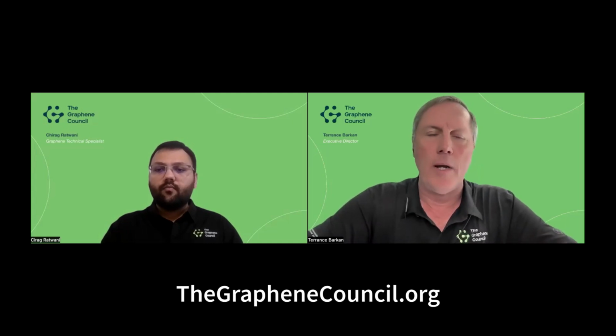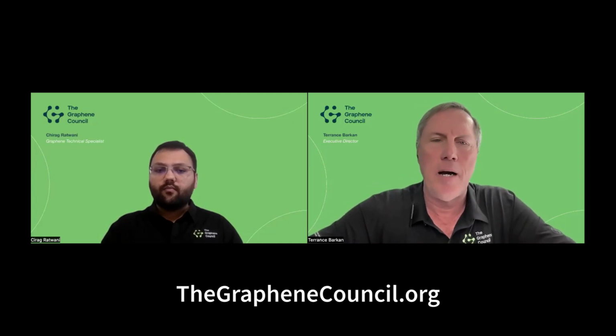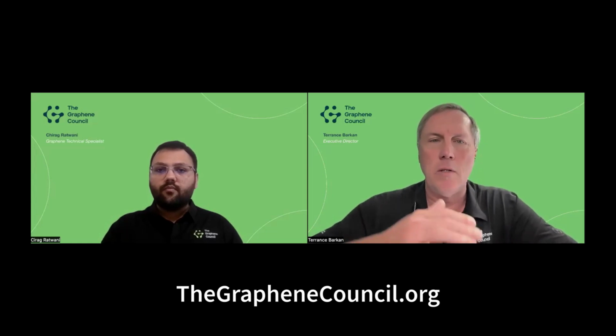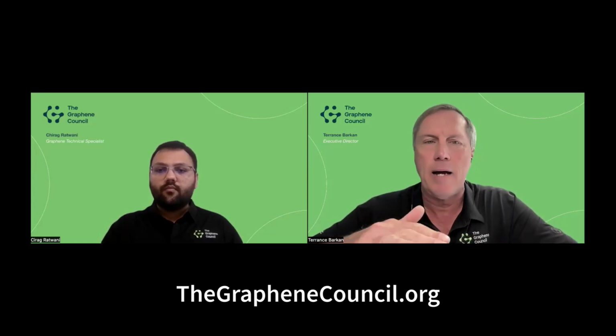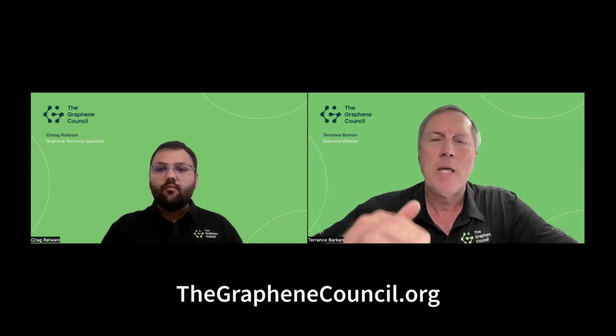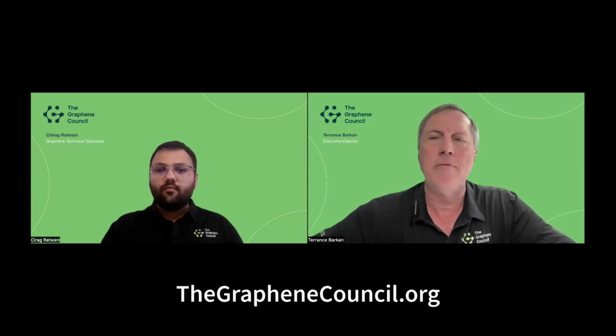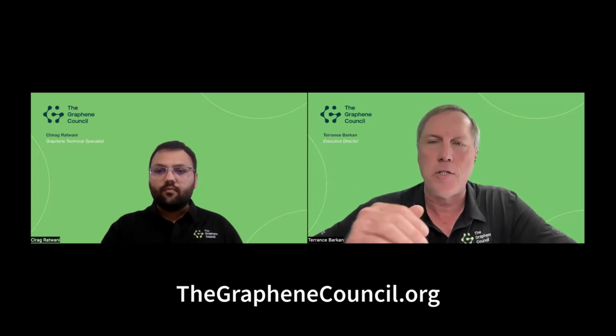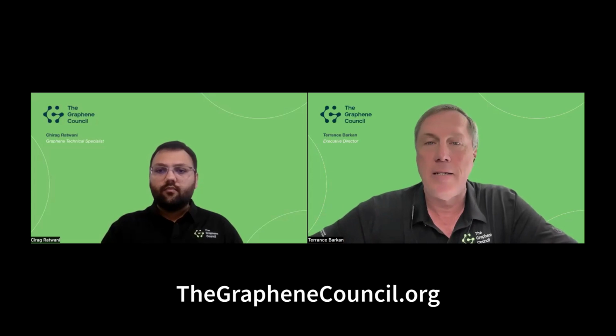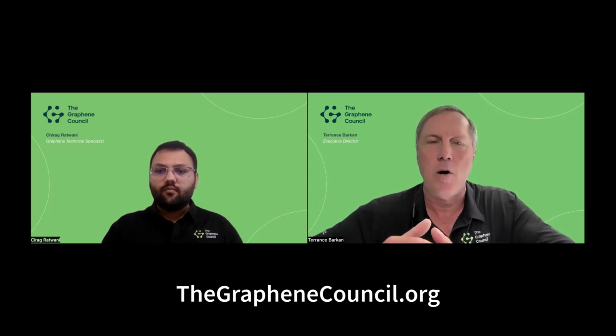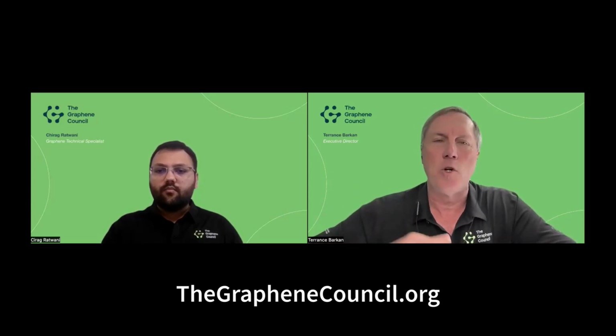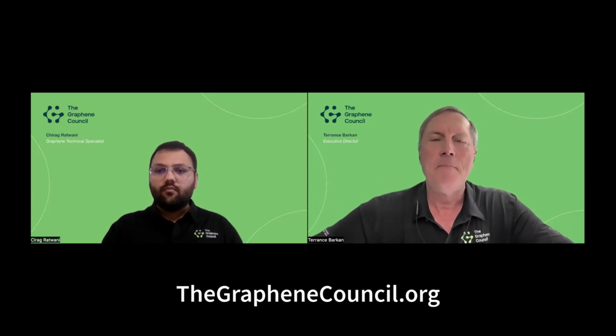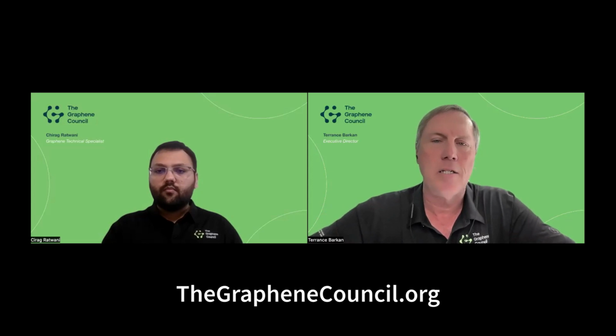It's also important to point out, although we discussed it, it may not be obvious, some graphene that's produced is quite homogeneous. So let's say 90% of the flakes are 5-layer to 6-layer graphene. In other graphene material that suppliers have, it might be that 10% of it is 2-layer, 30% of it is 5-layer, and 60% of it is 10-layer. And so it's not very homogeneous at all. You've got a big variation in terms of either layer count or lateral size of the primary particles in the graphene, and this can affect how it acts in your application.